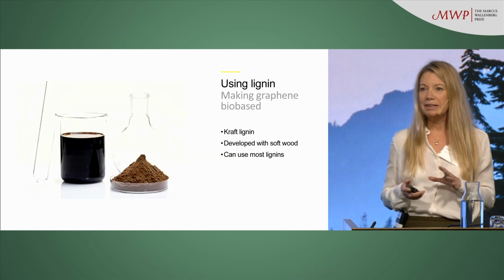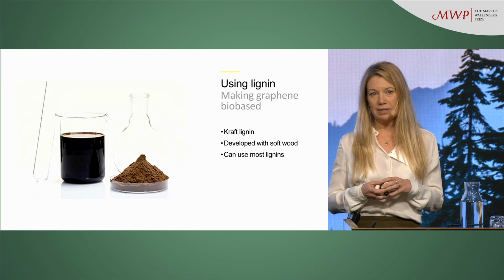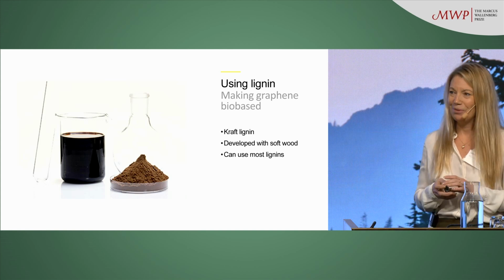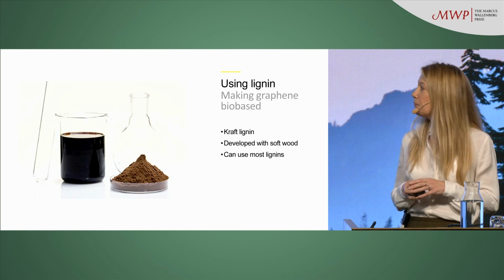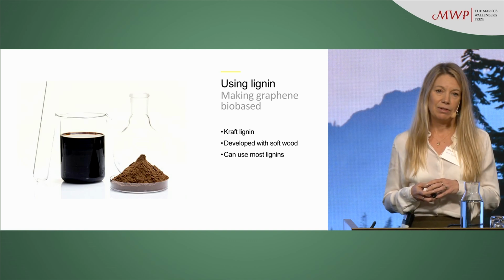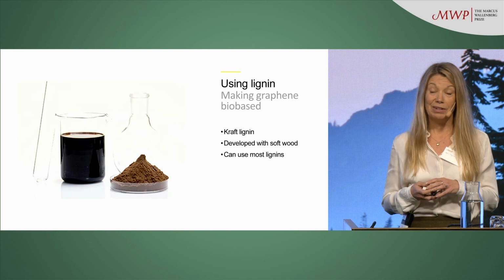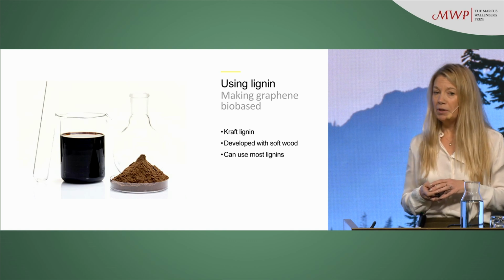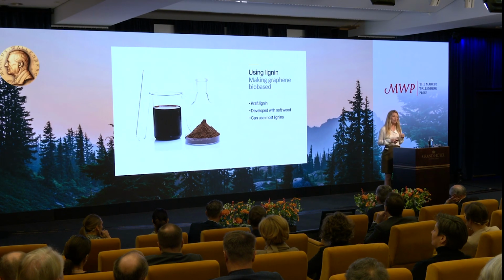And when it comes to the lignin that we use, we developed this process based on kraft lignin, actually from the LignoBoost process that Hannah was talking about. And we have mostly used the softwood lignin that is mostly available here in Sweden. And we have tried a lot of different lignins. And what we have discovered is that we are not that sensitive to the method of producing the lignin. They all work for us. We have quite a robust process, and it's not so sensitive.